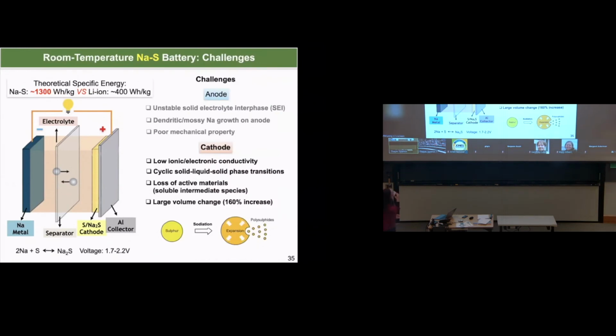For this battery system, there are a lot of challenges. I talked about the challenges from the anode side. On the cathode side, there's a series of challenges here. One is the low ionic and electronic conductivity, because both sulfur and sodium sulfide have low ionic and electronic conductivity, which is not good for the battery performance.